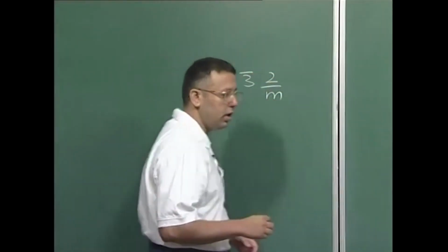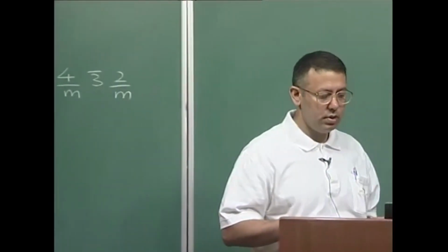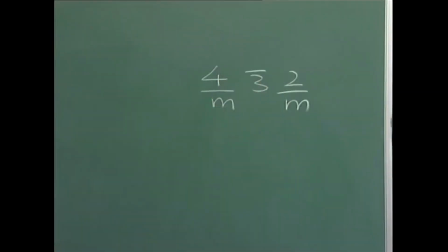So this is the symmetry of all cubic lattices, but cubic crystals can have symmetry which is lower than this. So for instance, cubic lattices always have fourfold symmetry, but a cubic crystal may or may not have this kind of a fourfold axis.